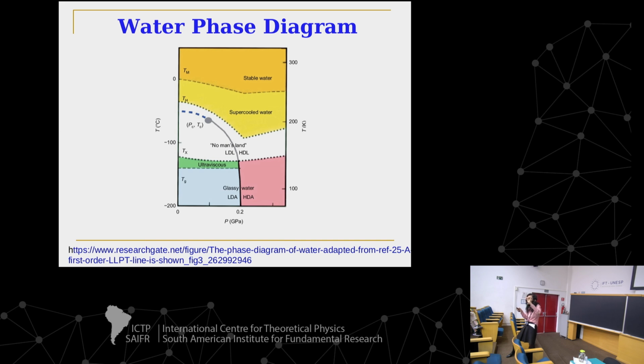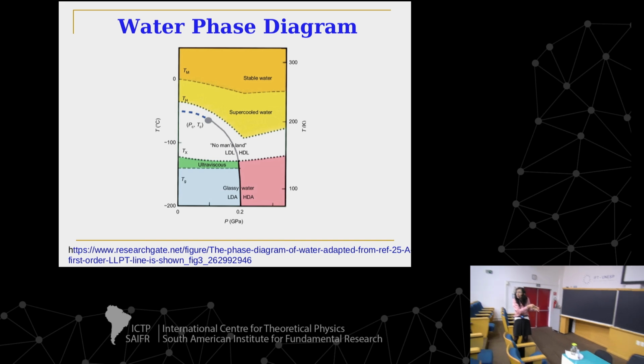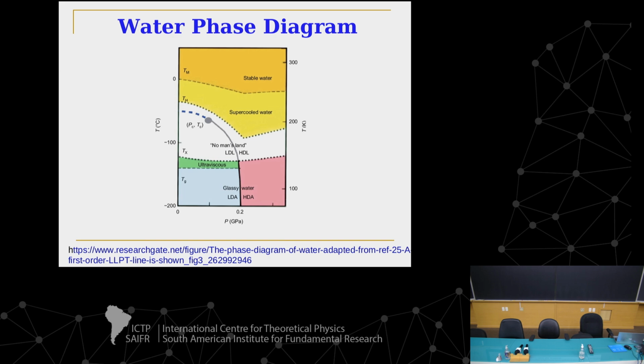So what people do is they confine water in cages, nano cages. With that, they change the position of this a little bit upper, and they see the peak, but they don't see the critical point. They see the continuation, because here, not even the continuation you can see because it's in this region. So you confine. Confinement usually moves the transition. So they confine to move the transition. And then they cross the dashed line, and they see peaks in the specific heat and the compressibility.